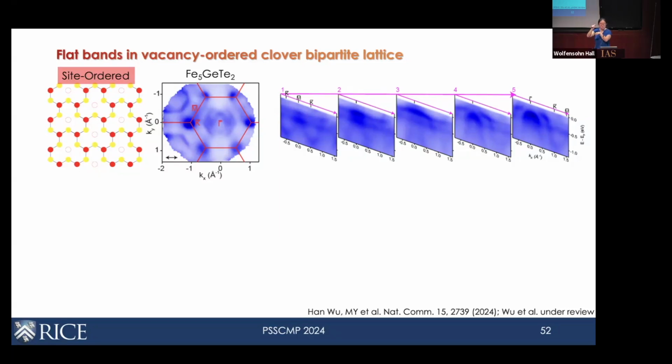But they won't disappear if you go across the ordering temperature, because it's not correlated across the sample. Locally you still have spin bands, but overall, what's spin majority and what's spin minority is no longer meaningful. Therefore, you lose the spin polarization. But for any site, the electrons still see the difference between being spin up versus spin down. Therefore, you still have the band splitting.